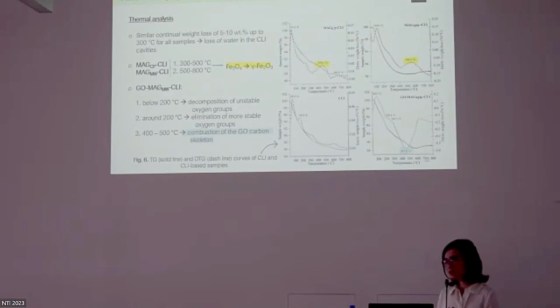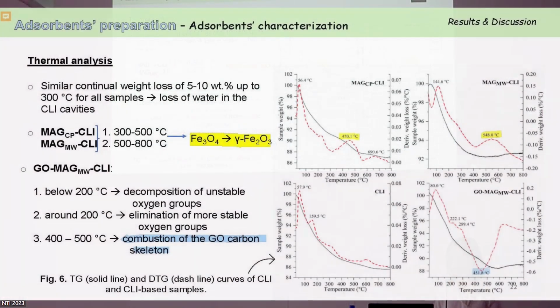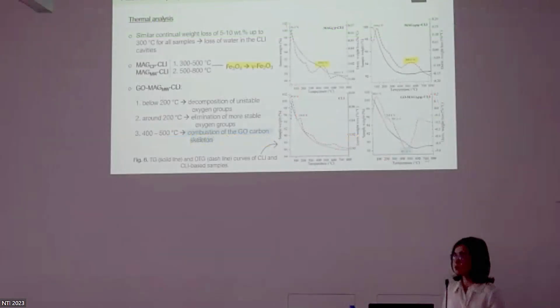The thermal analysis shows similar weight loss up to 300 degrees Celsius for all samples, which can be attributed to the loss of water in the clinoptilolite cavities. At high temperatures, the loss differs between the modified samples and clinoptilolite. This can indicate the transition of magnetite to maghemite for the magnetic clinoptilolites, and combustion of the graphene oxide carbon skeleton at around 450 for the samples modified with graphene oxide.